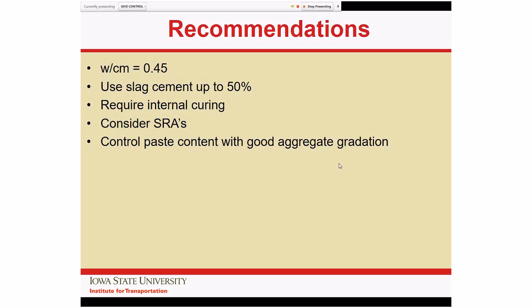So my recommendations moving forward: bridge decks should have a water cement ratio of about 0.45. I'm reluctant to go any higher because your permeability will be compromised. For a bridge deck, it's probably not a good idea to go too much lower because of changing the cracking risk. This number is pretty consistent with the literature. Slag cement seems to buy us a lot of properties: the improved permeability and the improved strength, partially due to the lightweight fine aggregate, partially because of the presence of the slag.